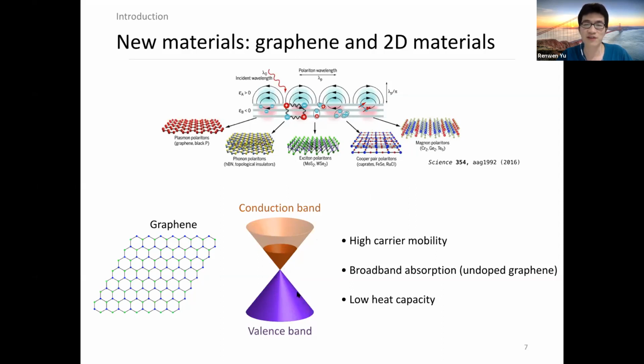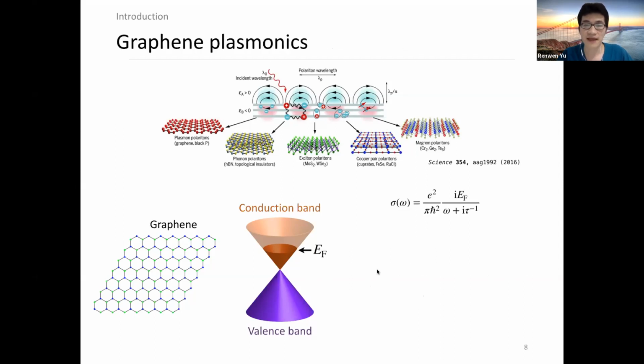Due to its peculiar band structure, graphene can have very high carrier mobility. It can provide broadband absorption of light. And due to its two-dimensional nature, it has very low electronic heat capacity. When graphene is doped to a certain Fermi level EF, and considering only its intraband transition, its optical conductivity can be expressed in this Drude-like expression. And as you can see, since it's basically a metal when it's doped, it can support plasmonic resonances, just as noble metals.